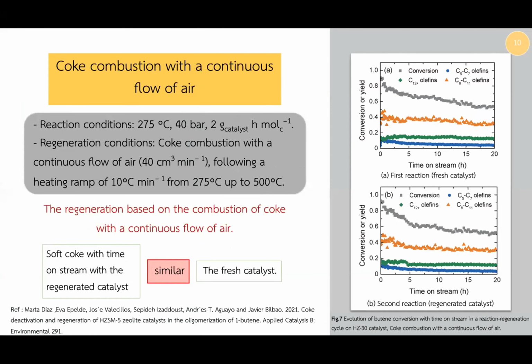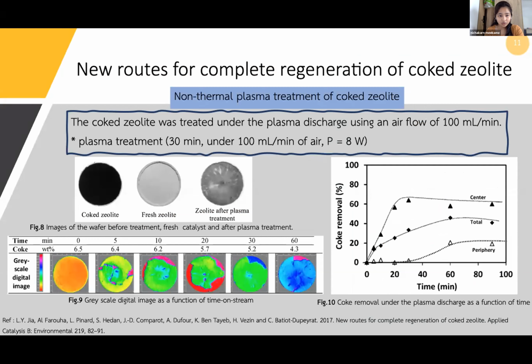For coke combustion with a continuous flow of air on this condition, as seen, the catalyst recovers its activity, and the evolution of conversion and soft coke yield with time on stream with the regenerated catalyst are similar to those obtained with fresh catalyst. For a new route for complete regeneration of coked zeolite, an alternative technology to overcome the difficulties associated with thermal regeneration of coked zeolite,